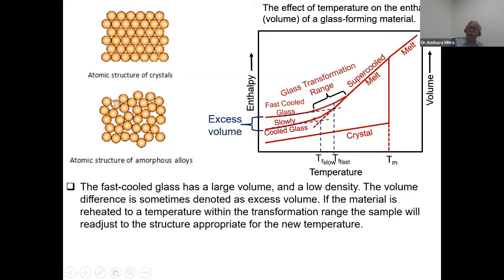The structural relaxation - as free volume exists, the density of the two phases was different. The amorphous alloy has less density than the crystalline alloy, and due to structural relaxation, there is a change in density also, but this change in density is not very prominent.